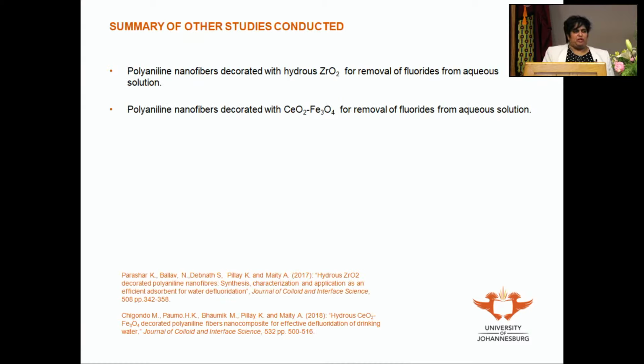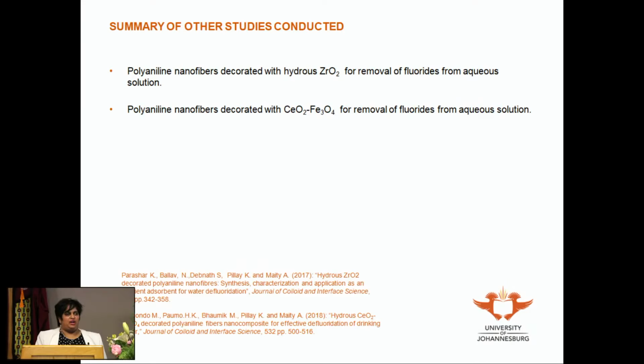The types of pollutants that we've worked with were not necessarily metal ions and organics only. There's a lot of work that we've done on fluoride remediation, and there are two studies in particular that I want to highlight here, where we decorated polyaniline nanofibers with a hydrous zirconium oxide material and also a hydrous binary oxide material for it to be effective for fluoride removal.